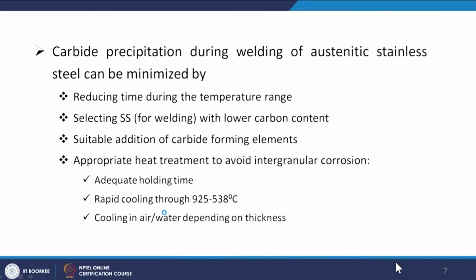Okay, so carbide precipitation during the welding of austenitic stainless steel can be minimized by reducing the time in the temperature range, selection of stainless steel for welding with lower carbon content, and addition of carbide forming elements. So like titanium, if we add it, those will form carbides more prominently than chromium, so that will retain the chromium. And appropriate heat treatment to avoid intergranular corrosion, like adequate holding time, rapid cooling through 925 to 538 degrees centigrade, and cooling in air or water depending on the thickness. Okay. Next.